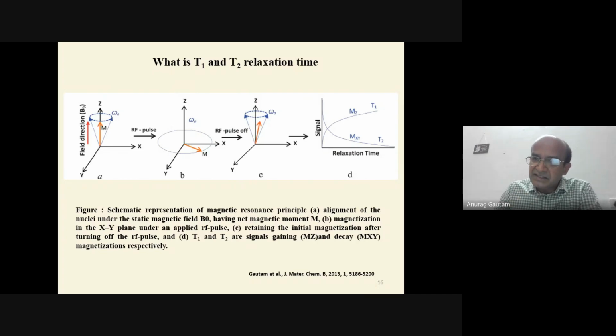So as I said, T1 is around 3800 milliseconds and T2 is around 36 milliseconds. So let's say by applying this measurement using contrast agents, we measure for a particular contrast agent. And we find it really shortens T2, maybe up to 4 milliseconds. So that material will be a T2 contrast. How much it gets shortened depends on the measured T1, T2 time.